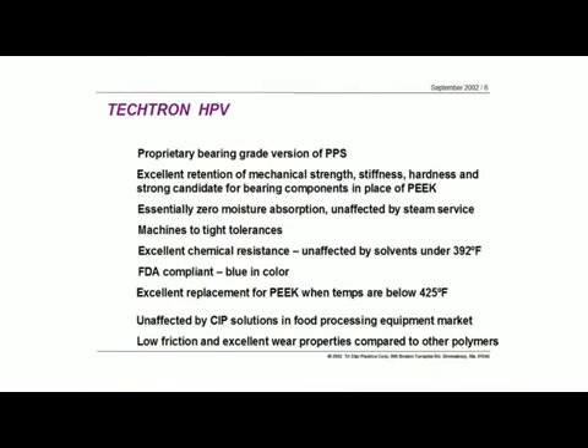You can hold tight tolerances on it. The chemical resistance, again, comes into play. It's not affected by solvents under 392 degrees Fahrenheit. So again, we can use this in a lot of chemical applications in terms of pumps and valves and things like that. The HPV is also FDA compliant, even though it's not white, it's blue. The straight Techtron is white, but the HPV is a very distinguishable color of blue. Again, under 425 degrees, it's a great replacement for bearing grade PEEK.